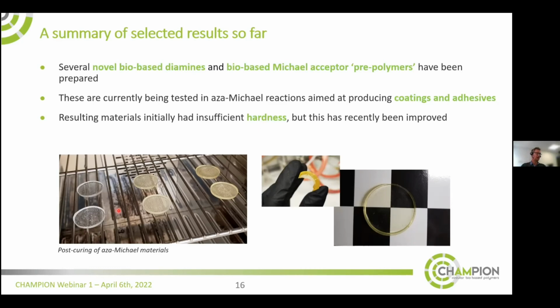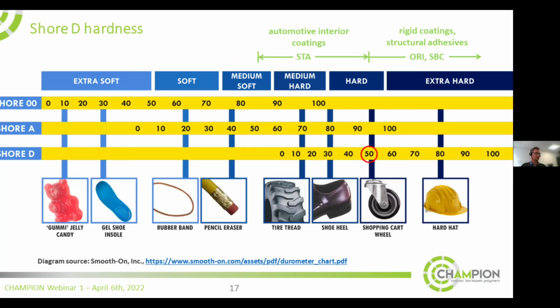So here you see these are lab scale experiments. So these are some of the materials that we produce. And these are usually post-cured briefly in an oven to see if any increase in mechanical properties can be obtained. So hardness is a very important property for the applications that we are targeting. And here you see the so-called Shore D or shore hardness scales. You have different shore hardness scales. The very soft materials are so-called Shore OO. Then you have intermediate hardness for Shore A. So these are still relatively soft, but we are aiming for relatively hard materials in the Shore D range.